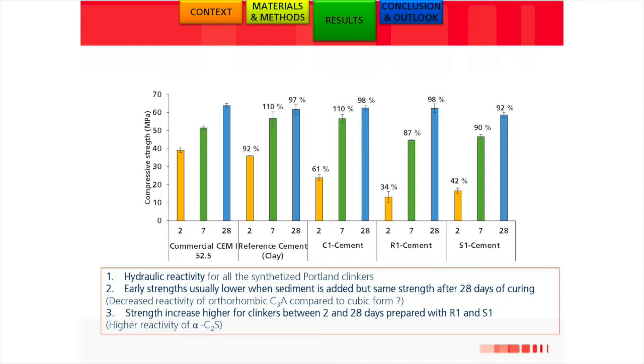Here is the data we obtain with these sediments. Obviously, after 2 days of setting, the compressive strength is not as good as the commercial cement, because of minor phases which develop during sintering. However, in the long term, we obtain characteristics quite close to the commercial product. This means that by substituting 25 or 30% of the usual raw material with sediments, we obtain a cement with characteristics very close to a commercial product.